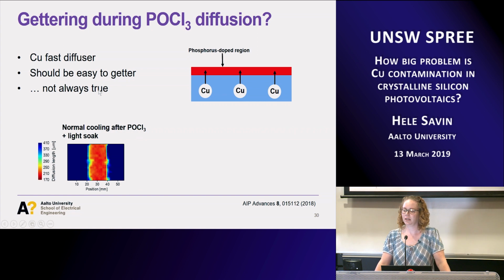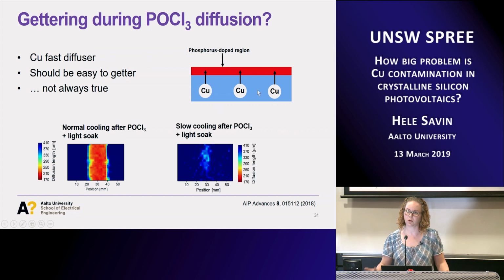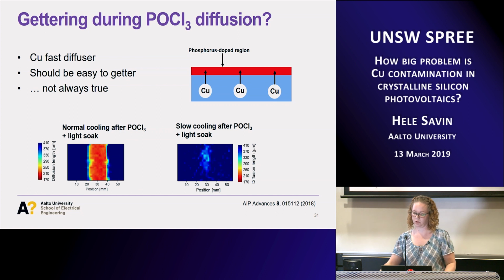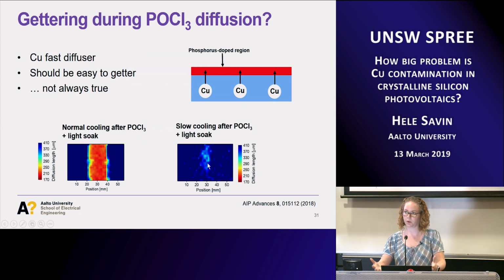So if we just ran the normal POCl diffusion gettering experiment, we have again the spots there. We do a standard industrial type of POCl emitter, and we measure the lifetime. Initially we don't see anything, but after light soaking we clearly see that the copper spot appears there. However, if we do the cooling after this POCl diffusion relatively slowly, so instead of pulling out the wafers quickly from our furnace, we give enough time for copper to diffuse to the emitter. In that case, we saw clearly that copper was gettered to the emitter, and we didn't see almost any traces of copper anymore if this slow cooling was used.